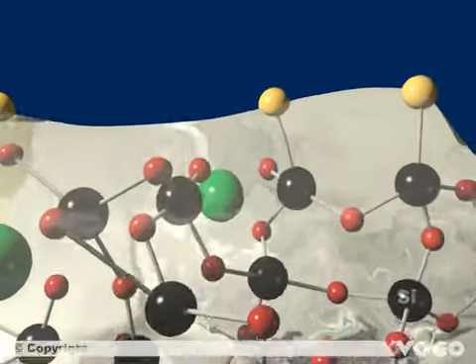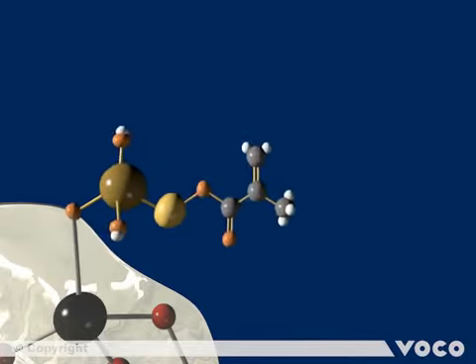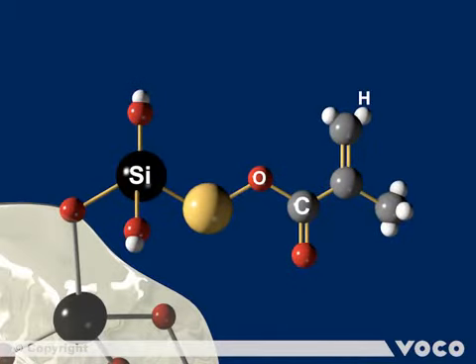The surface of the glass particle is modified, shown by the yellow spheres. The special coating is done by a silanization process which takes place in an upstream reaction. For this purpose, methacrylic silane compounds with a double bond are used. They enable the connection to further double bonds, which means further elements of the matrix. The double bond is highlighted in red.